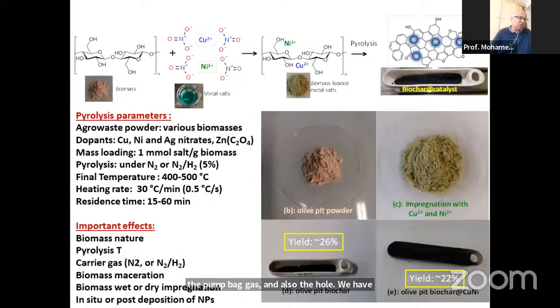Usually in the literature, when we want to produce biochar with a loaded nanocatalyst, the biochar is formed first and then modified with metal ions, which are reduced on top of the biochar. In our case, we have used a completely different and more straightforward approach. We start with the biomass. We prepare the metal ion solution, for example copper and nickel nitrates. We impregnate, it's called the wet impregnation method, and we pyrolyze the biomass powder with impregnated metal ion salts.